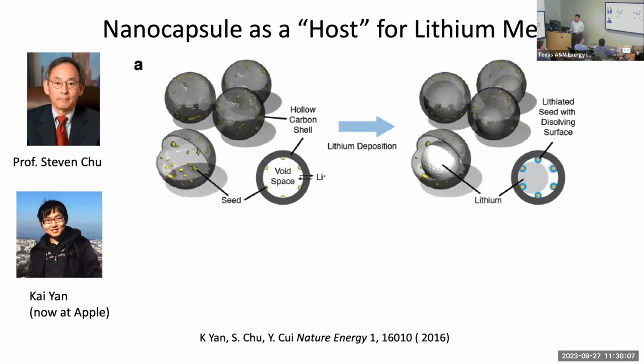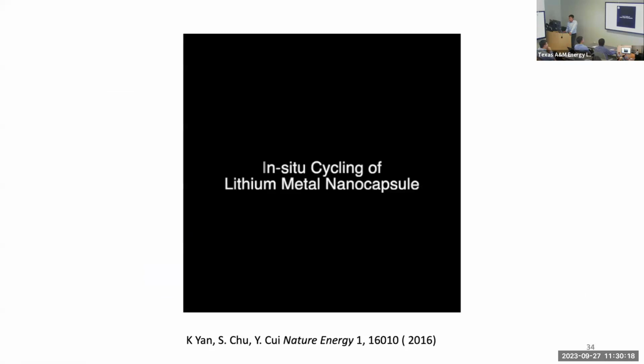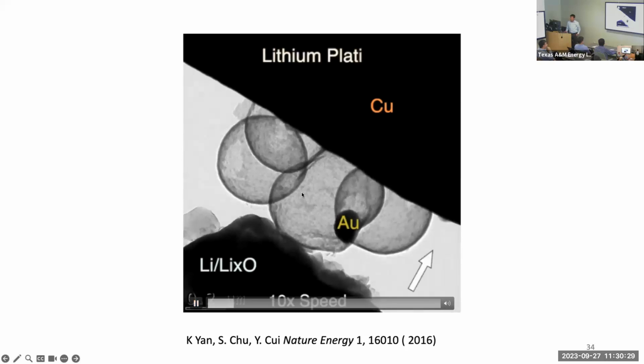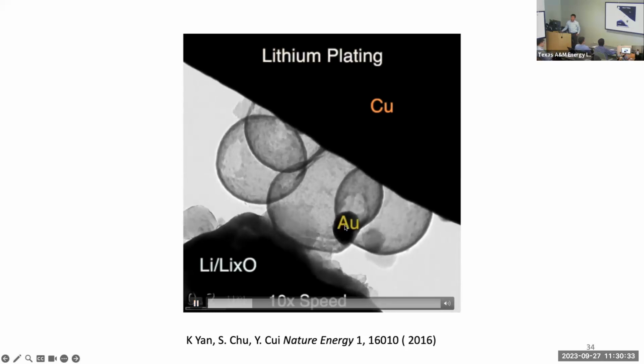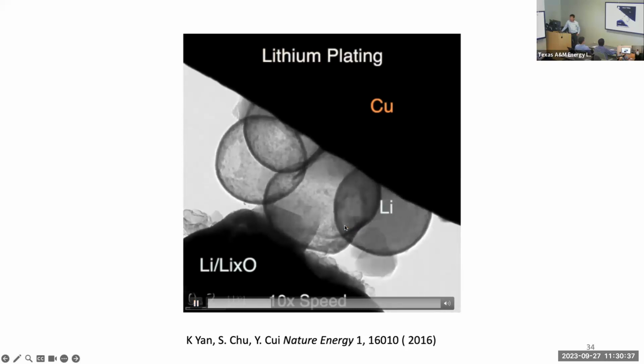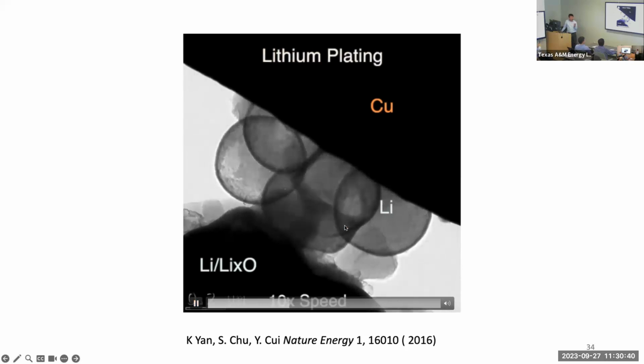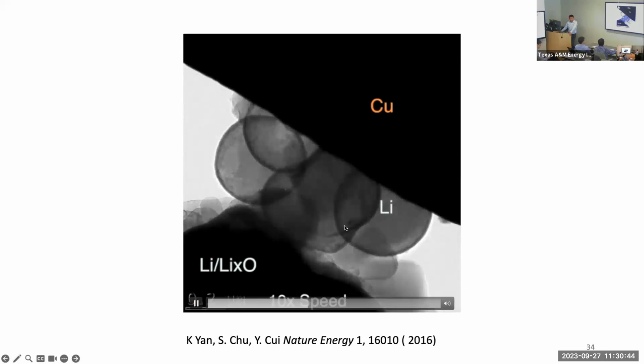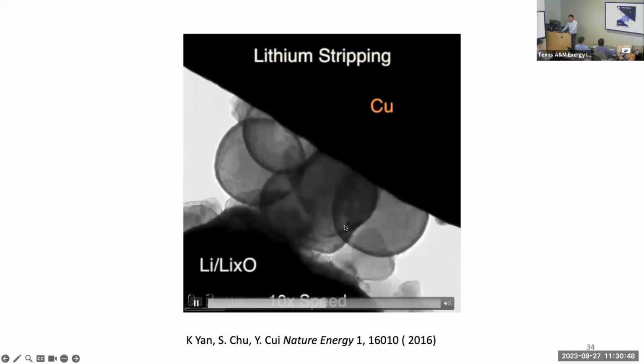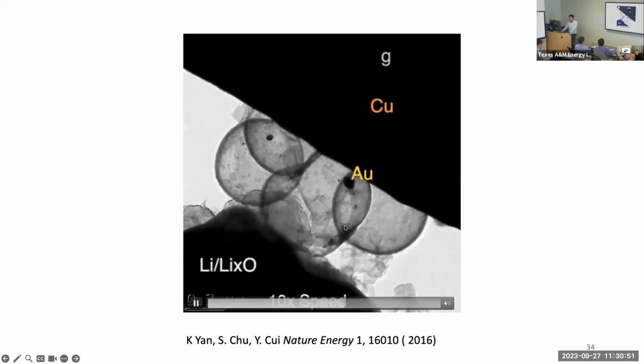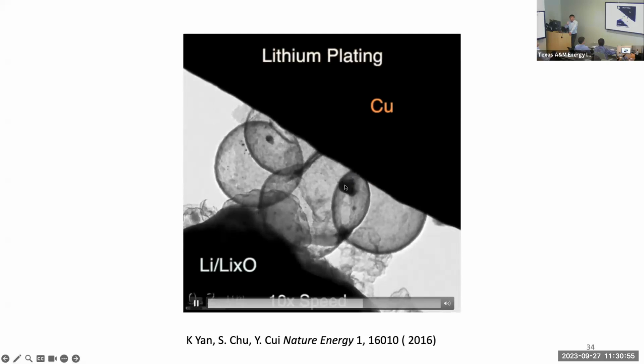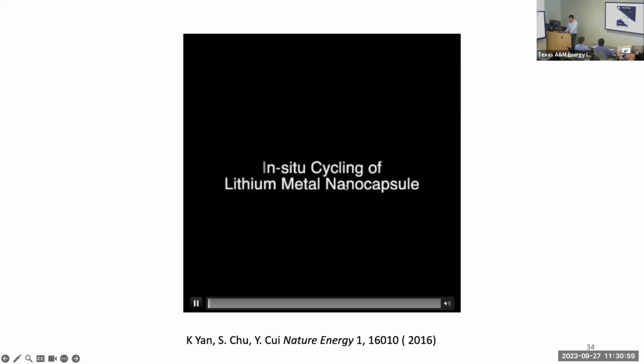Now this hollow carbon sphere will isolate metallic lithium from the organic electrolyte. You can build a stable solid electrolyte interface. So we made this structure. Let me show you this TEM video right here. TEM technique is really powerful for us to understand. What you see is this hollow carbon, this gold seed inside, and then you deposit lithium electrochemically. You see gold get dissolved away. Once you strip lithium out, you are going to see in a second the gold nanoparticles will come back, the black dots. So this really clearly shows gold helps the nucleation and deposition of metallic lithium.